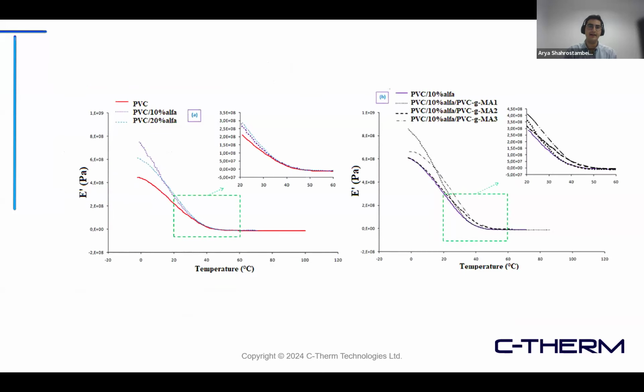On the left-hand side, you see that by adding 10% of alpha fiber to the composite, it has gained storage modulus, meaning that the material has become stiffer, and followed by adding more fiber, it has become even stiffer, and it has gained more storage modulus. On the right-hand side, the 10% PVC alpha fiber composite has been used, and it's a comparison between different compatibilizers with the same composite. And as you can see here, we again have an increase in storage modulus, or higher stiffness, by adding different compatibilizers.